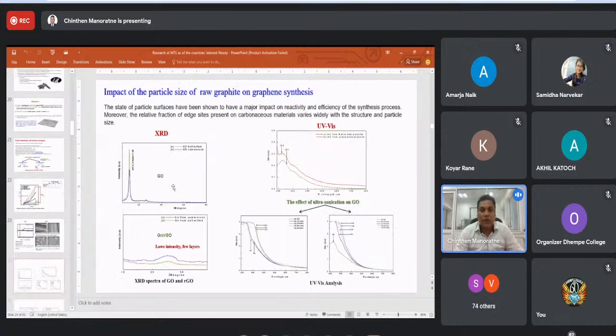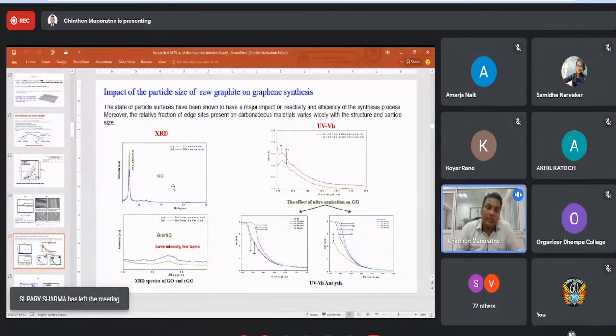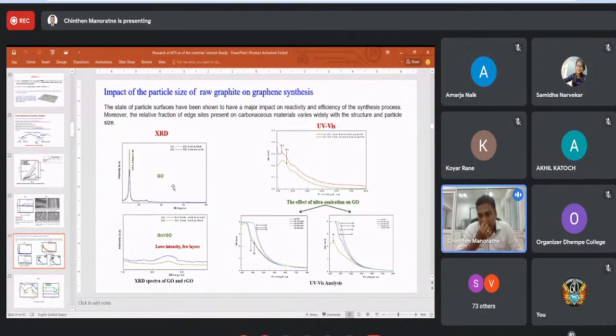Okay. Now what we actually did, we synthesized graphite oxide and reduced graphite oxide, that is graphene, from commercial graphite powder, that is the larger graphite powder, and the ball mill or smaller graphite powder. There you can see the clear characteristics. If you look at the XRD, you can see these intensities increase for graphite oxide synthesized from reduced particle size graphite. And if you look at this UV graph, you can see the absorption is very high in reduced particle size graphite oxide.